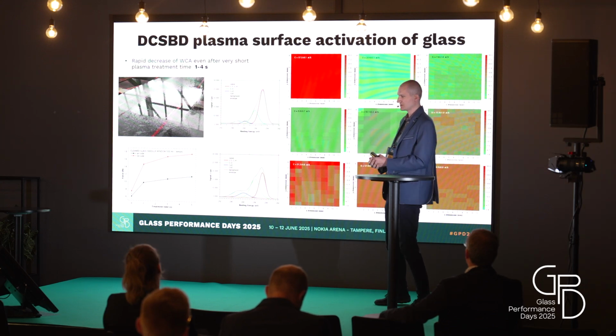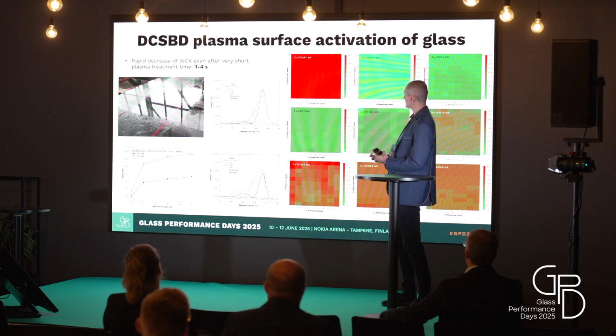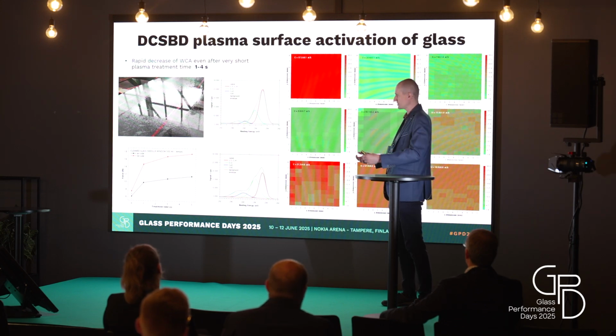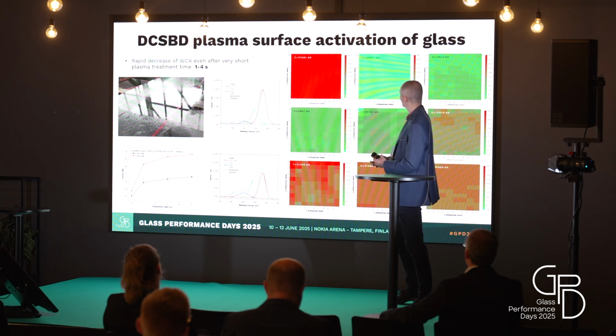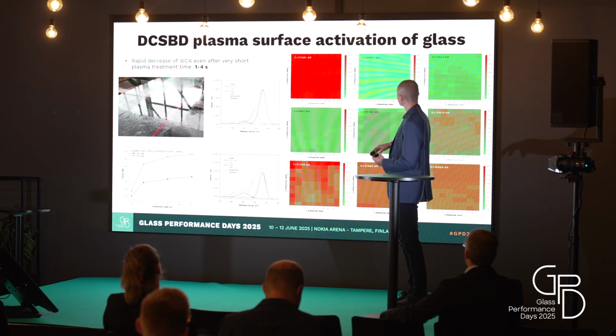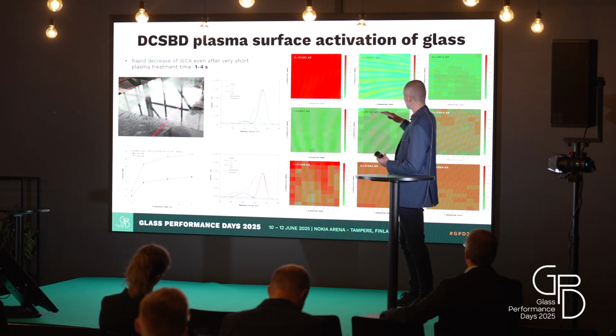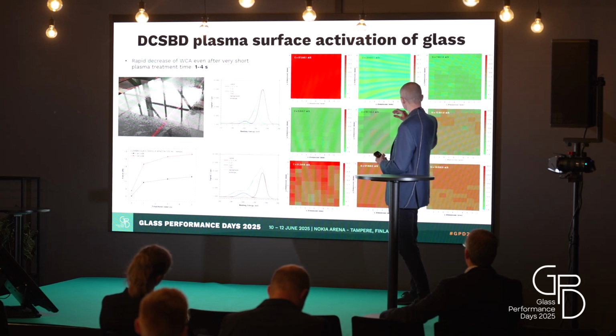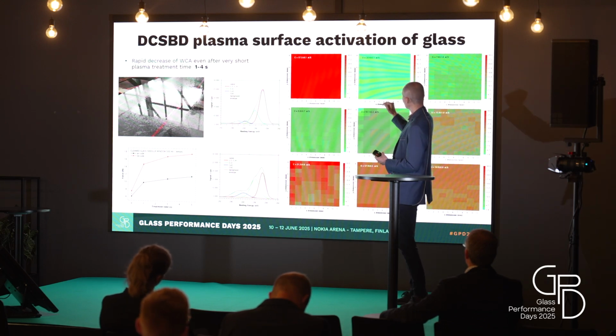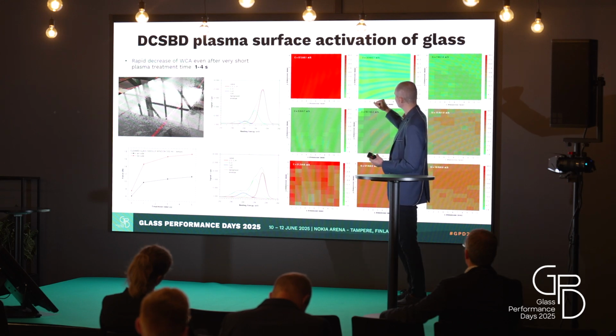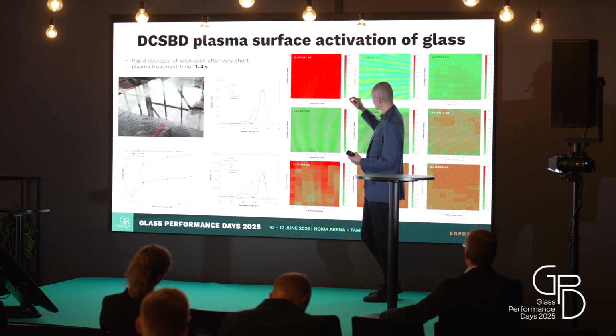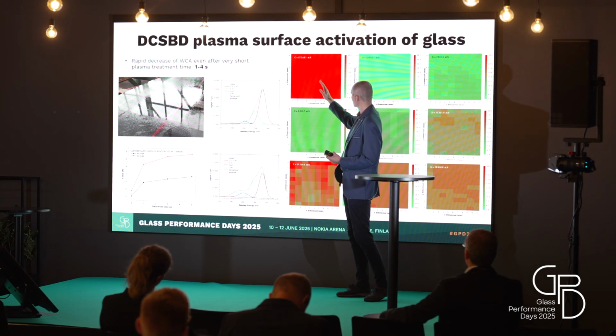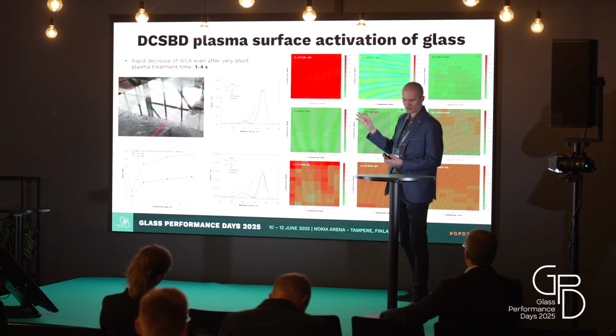What is very important is also the uniformity improvement of the glass surface, because when we do the cleaning, we want to maintain that the surface will be uniform, homogeneous. And using these images, I just try to show you that we can do the cleaning, and we also improve the uniformity. Here we have the XPS data, which tell us about the concentration of surface carbon, oxygen, and silicon on the glass surface.